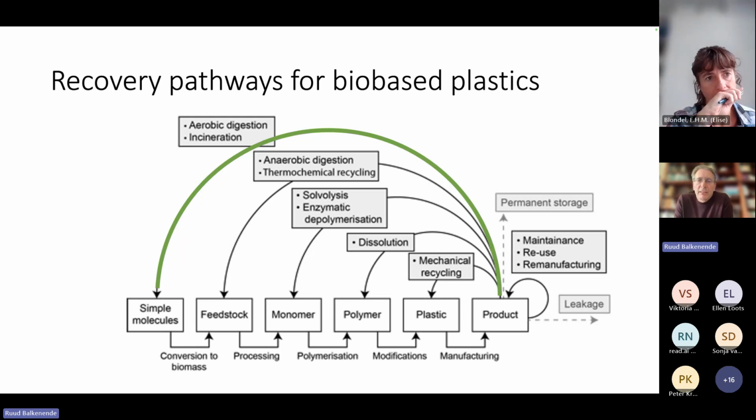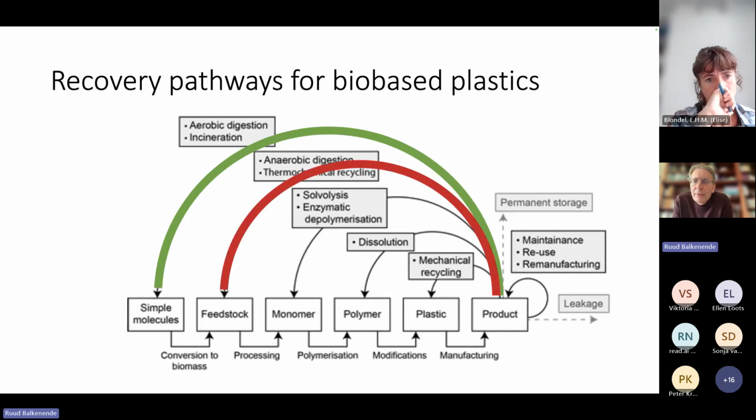But when this takes place in the atmosphere, you run the risk of adding methane, which has a far higher global warming potential than carbon dioxide. So what should be avoided is uncontrolled biodegradation, as this runs the risk of being more detrimental than burning ordinary plastics. So throwing a biodegradable product as fertilizer on soil, as sometimes is claimed as beneficial in, for instance, cradle to cradle, is nonsense and should be avoided at all costs.